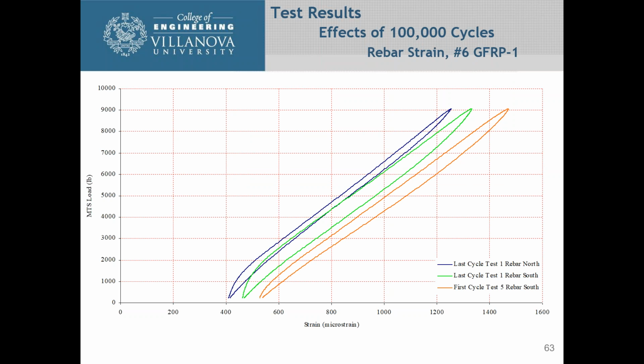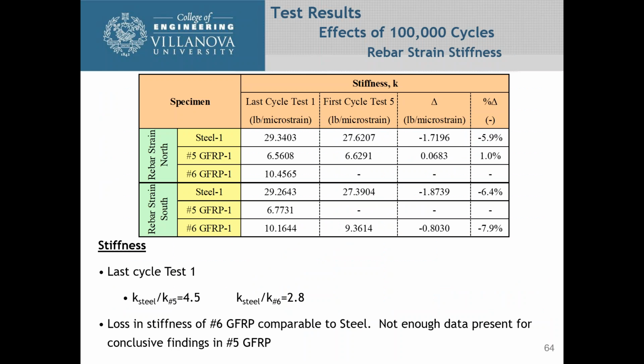And you can see through here that on this one, the blue bar is the last cycle of test 1, and that's the rebar on the north side. And the green is the last cycle of test 1 on the south side. But then we only have the red one, which is the first cycle of test 5 on the south. We lost the north rebar. So you can see again, as you go from comparing the green one to the red one, that the stiffness of the rebar decreases after 100,000 cycles.